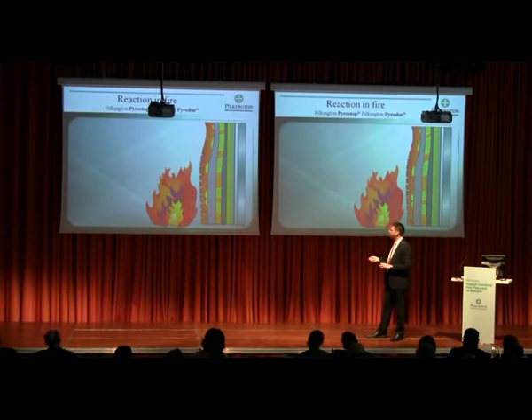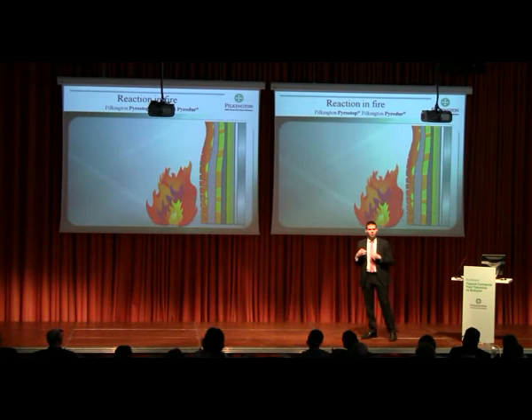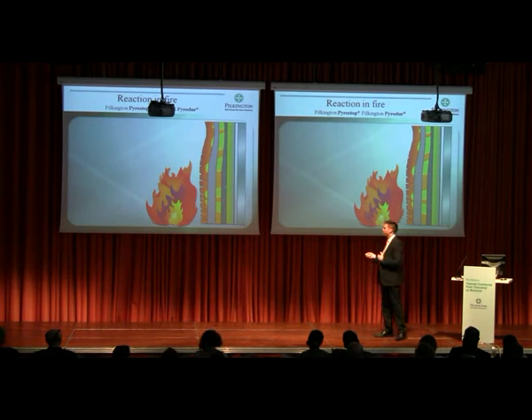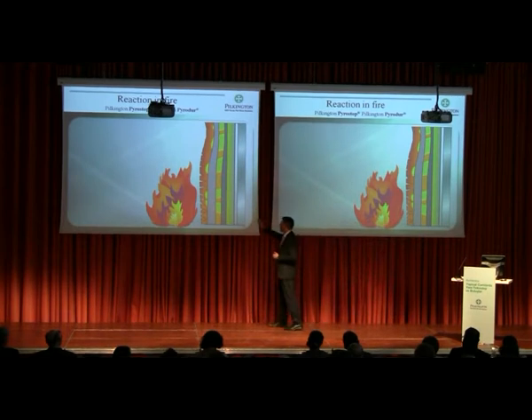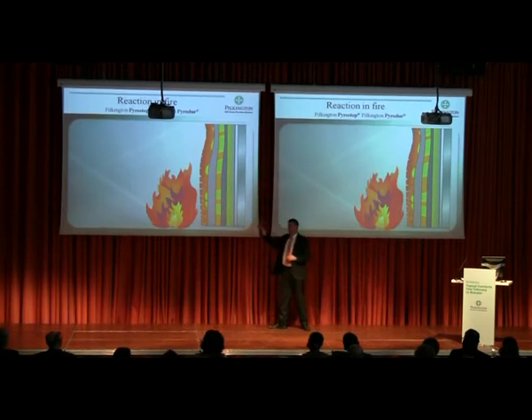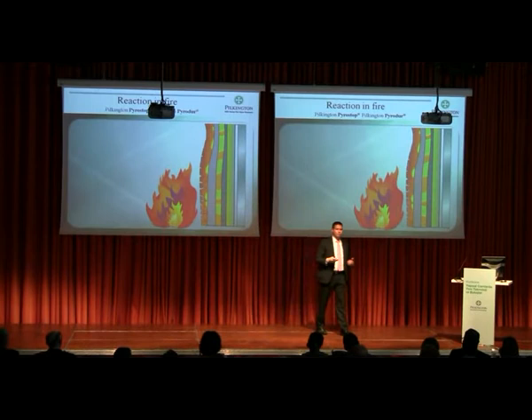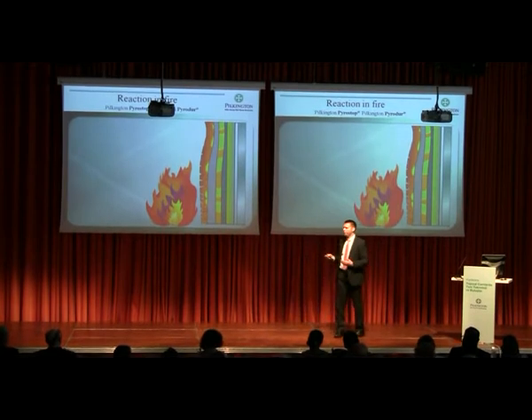What happens is that in this interlayer, which is foaming up, there is some water included. And this water is vaporizing, so the whole construction and the whole glass is cooled down to a certain level. For such insulated products, we measure temperatures on the unexposed side after 30 minutes, after 60 minutes, after 90 minutes, whatever we would like to achieve.